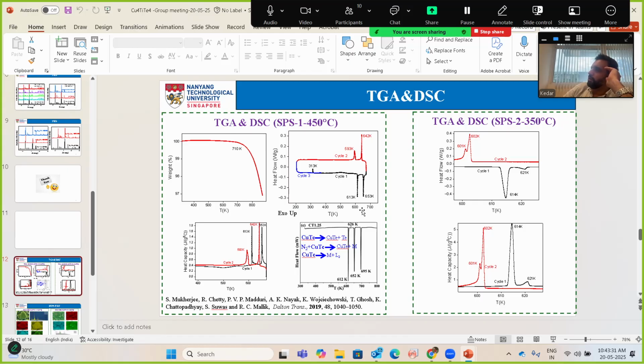So you just take the powder and create a batch of 6, and then Haiwan knows how to control different temperatures. You can just anneal at the different temperatures and look at the phase. It's very easy to do, something you can finish in 2 hours. Why don't you do that with Haiwan? This will complement your in situ XRD results. It'll also give us some extra information on whether this technique that Haiwan uses is complementary to in situ XRD.